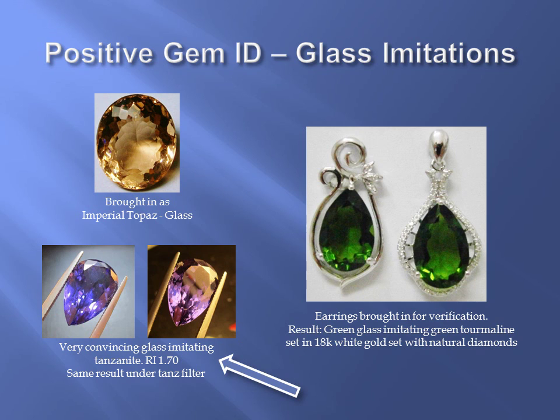This was an interesting stone that was imitating tanzanite. It's actually glass. The refractive index overlaps with tanzanite, and it was also showing red under a tanzanite filter. It's the first time I've seen glass give the same result as tanzanite under the tanzanite filter.